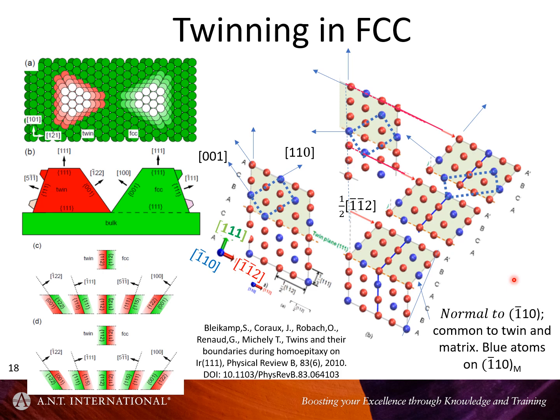So although it's a simple mechanism for deformation, depending on which plane you're interested in, the orientation relationship between the twin and the matrix can be a little bit complex, as in those planes which are parallel can be, for instance, the 1-1-1 plane, this particular 1-1-1 plane in the twin is common to the 5-1-1 plane in the matrix.